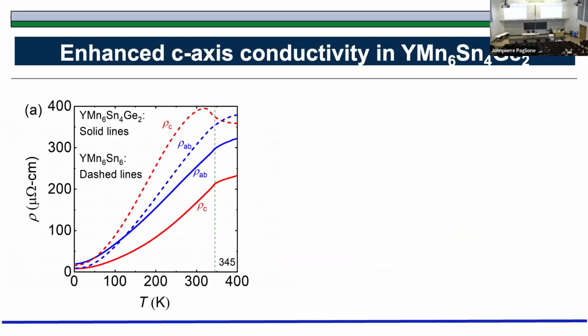So these dotted lines are for the parent compound, okay? This one is for C-axis resistivity. The blue dotted line is the in-plane resistivity. You see the same in the germanium compound. Then, this is a doped compound. Usually when you dope, you are messing up with the structure, and then your resistance, you expect to increase. Here the resistance becomes smaller, because this is a complete replacement, right? So you are replacing whole tin with germanium. So it's still a line compound.